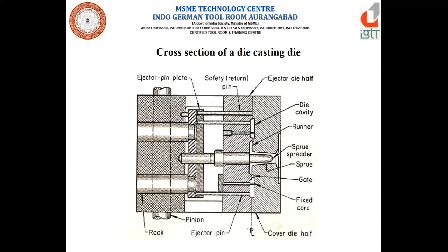Self-cleaning of the vent can be ensured by making the vent 0.5 to 0.6 mm thick for the first 40 to 50 mm of length, and then decreasing this thickness to 0.1 to 0.2 mm for the lead out of the die.